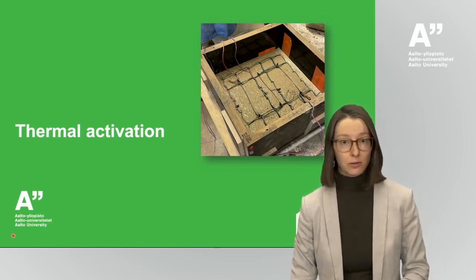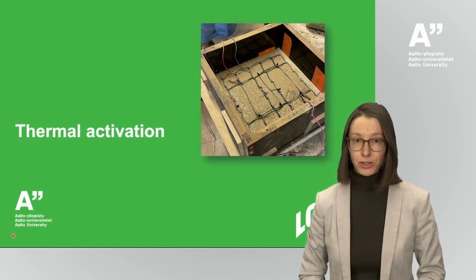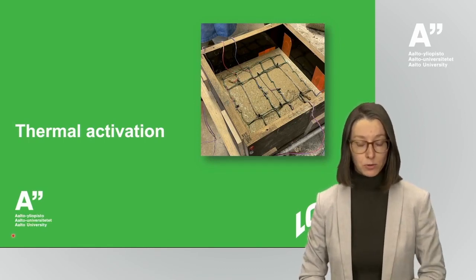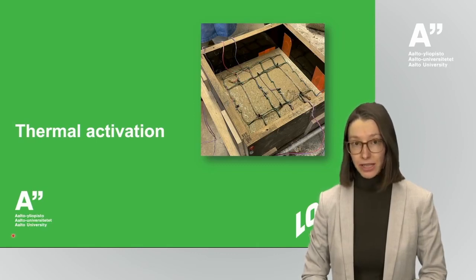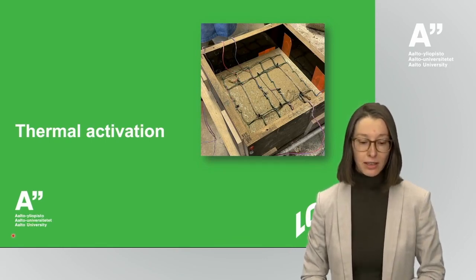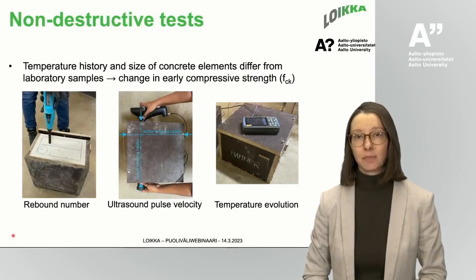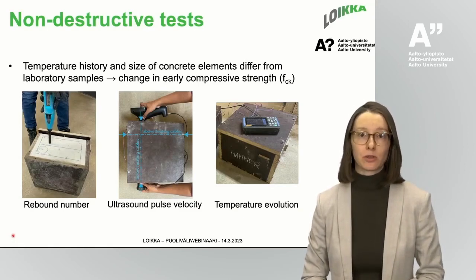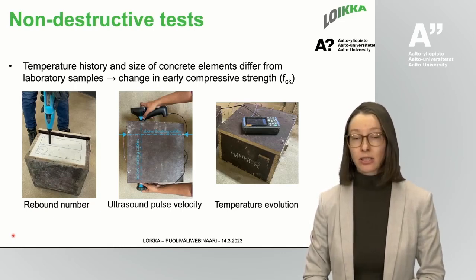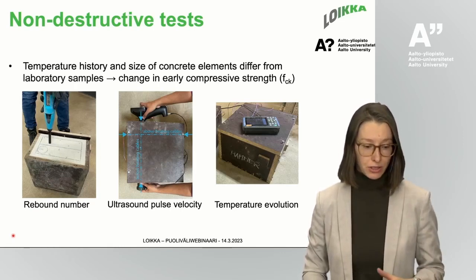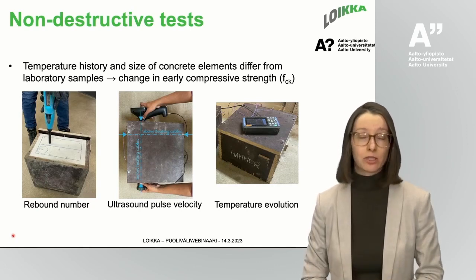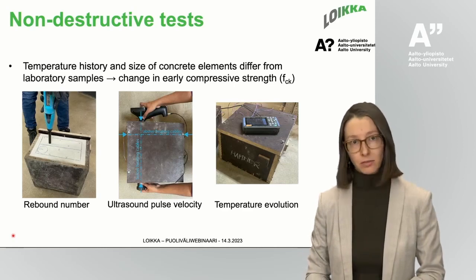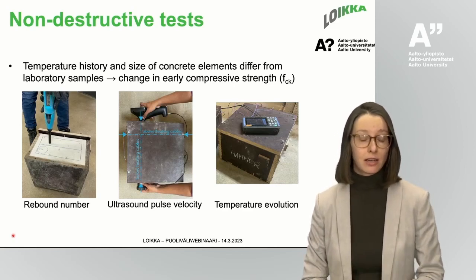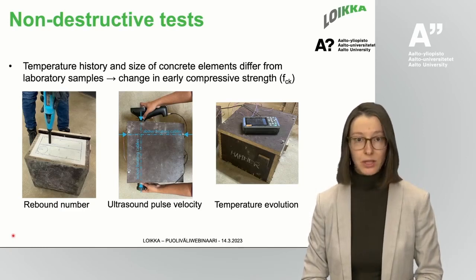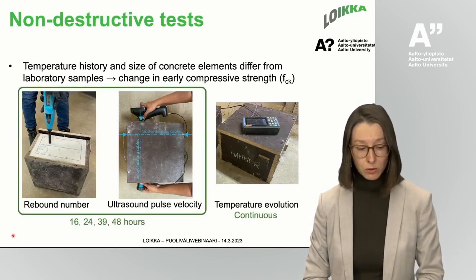It is needed, as Anna said, for activation of slag, and as you can see on the picture, we used quite big molds for casting, because one of the reasons for that, we need to place the cables and it needs space. That is why the mold's quite big. The second reason that we needed the methodology which allows us to estimate early strength development in non-standard molds, which have different temperature development due to the different amount of cement which produce different amounts of heat and affects the strength development. So for that purpose, we used rebound hammer and ultrasound pulse velocity.